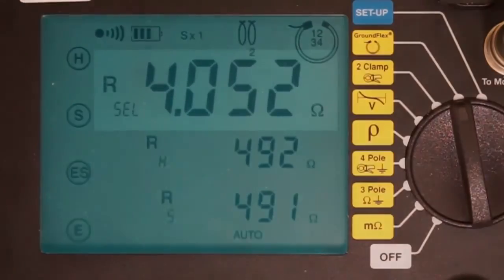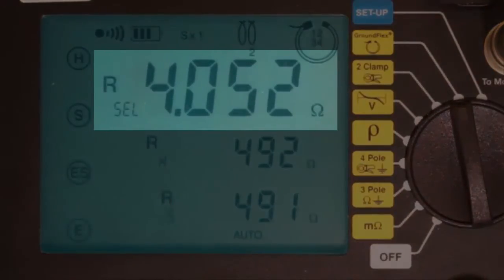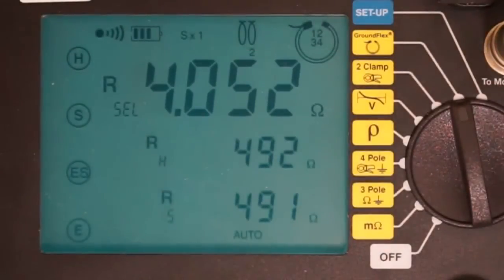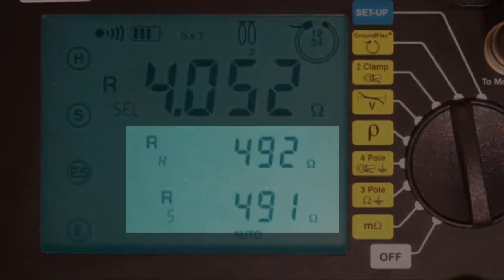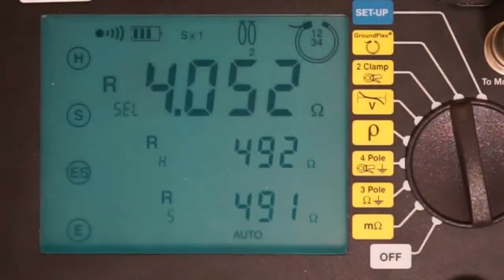At the top of the screen is the total tower resistance. In our test, this is the resistance for the combined 4 tower legs, which is around 4 ohms. A properly grounded tower should produce a measurement below 15 ohms and ideally below 5 ohms. Note that this screen also shows the resistance measured between our output probes and ground electrodes. For each electrode, resistance should be below 1000 ohms, as is the case here. Resistance higher than 1000 ohms can call into question the integrity of the measurement results.